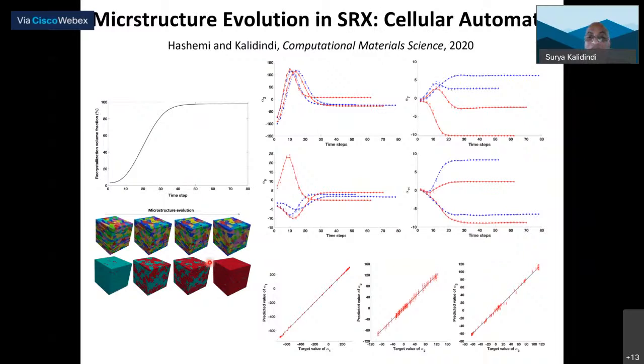You can also do process evolution. In this case, this is static recrystallization modeled by cellular automata. In those models, one looks at the evolution of microstructure. Again, the solid line is the prediction and the dots are the ground truth. You can see that they're pretty close. Because we're looking at microstructures in terms of PC scores, the predictions show how well the low dimensional representation of the microstructure is captured in this evolution. So it's not restricted to just static problems. You can do temporal evolution of microstructure.